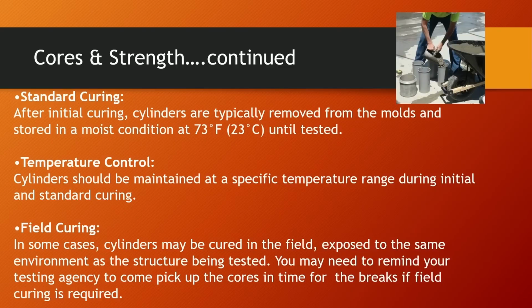Standard curing. After initial curing, cylinders are typically removed from the molds and stored in a moist condition. Temperature controlled. Cylinders should be maintained at a specified temperature range during initial and standard curing. And then again, we talked through field curing. In some cases, they can be cured in the field, exposed to the same environment.